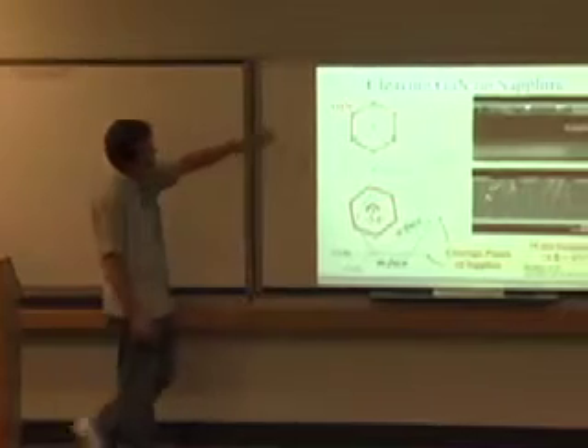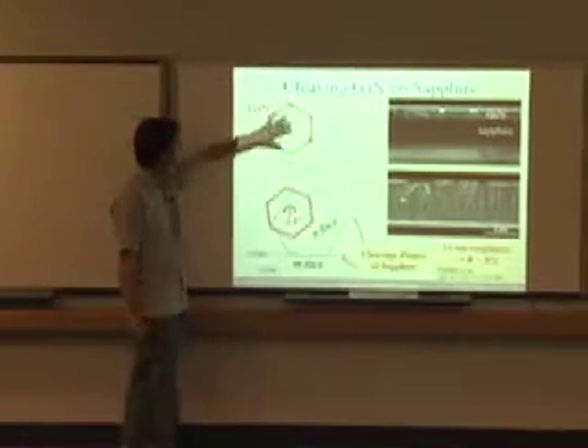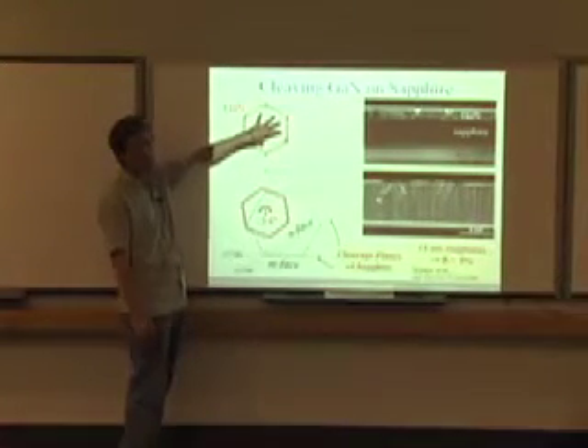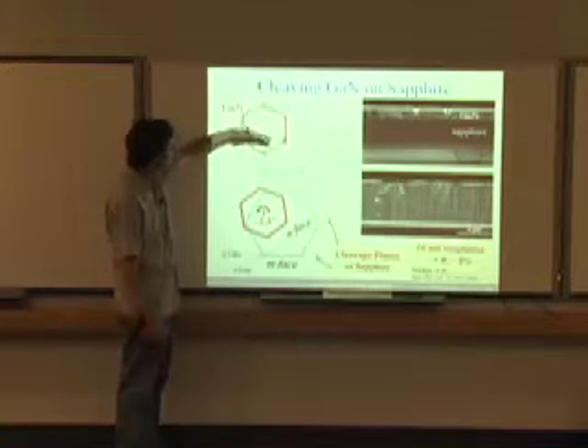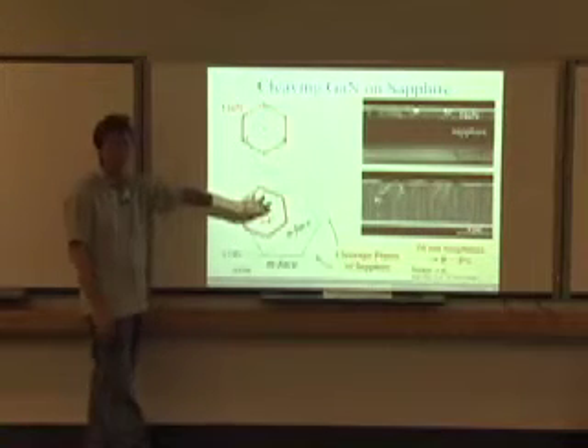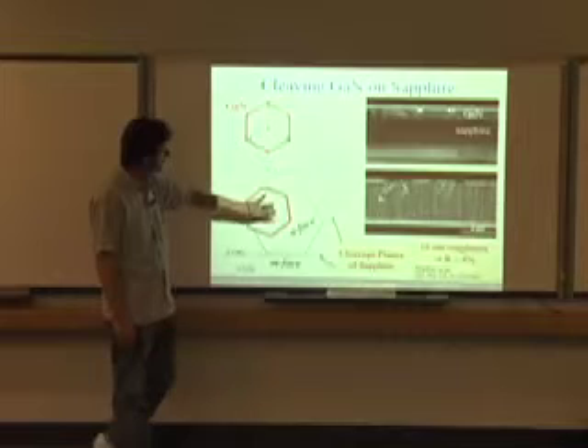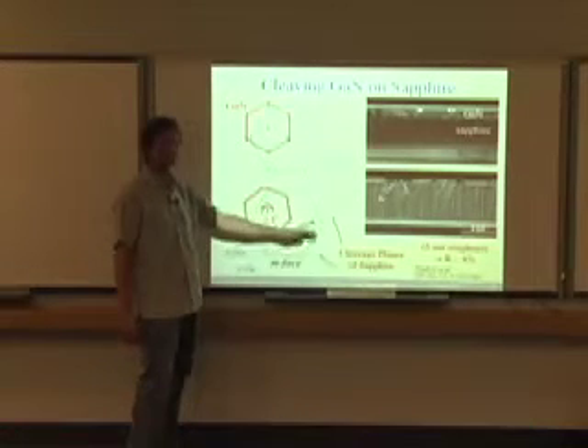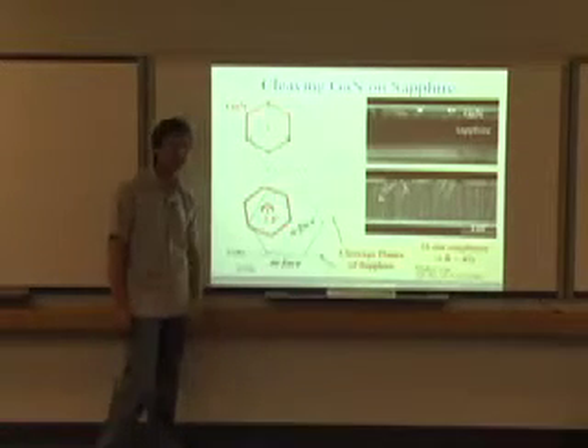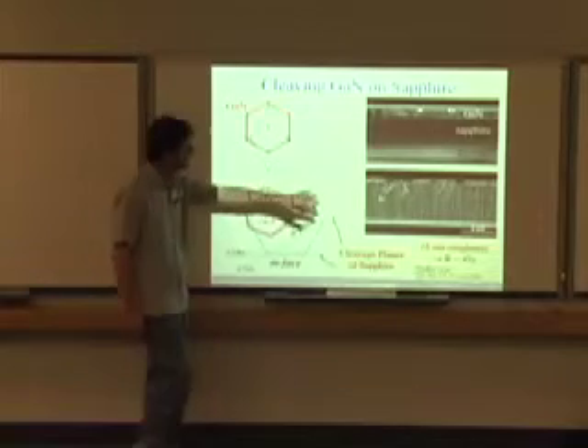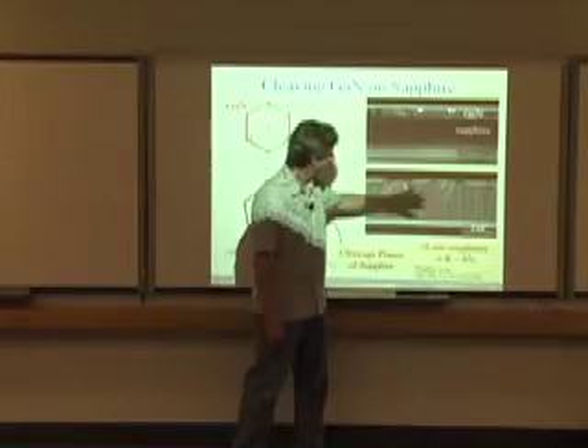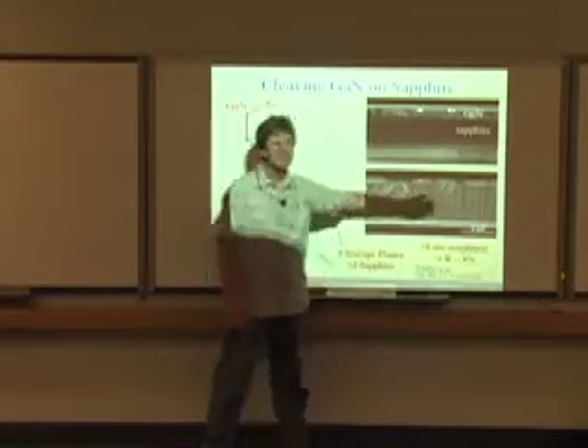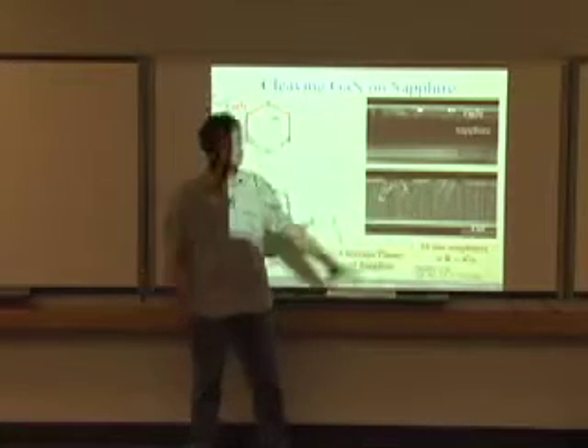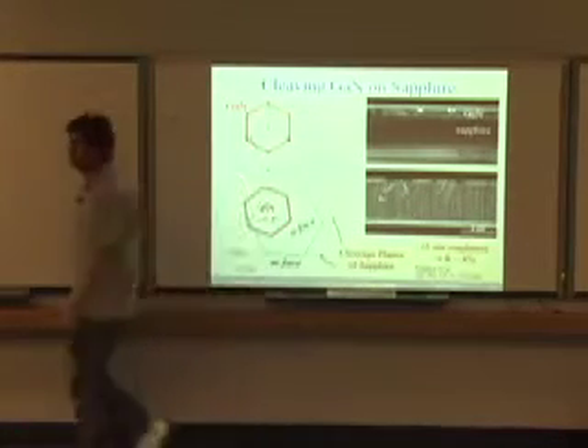Cleaving gallium nitride on sapphire, then you may think it seems like it should work. Gallium nitride should just align on sapphire, and then you should be able to cleave along one of the planes. Unfortunately, it twists a little bit when it actually gets grown on there. And so some of the cleavage planes on sapphire are the A face and the M face. And what you end up with is kind of a terraced face that has some roughness to it. So getting good reflectivity is a bit challenging on sapphire, on C face.